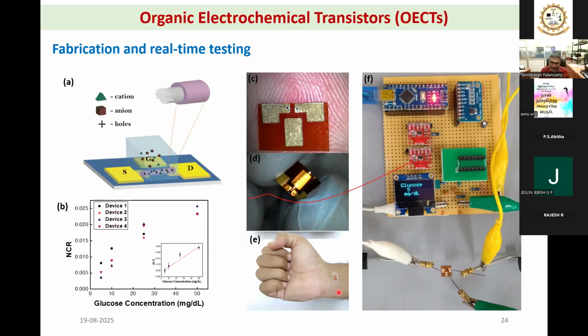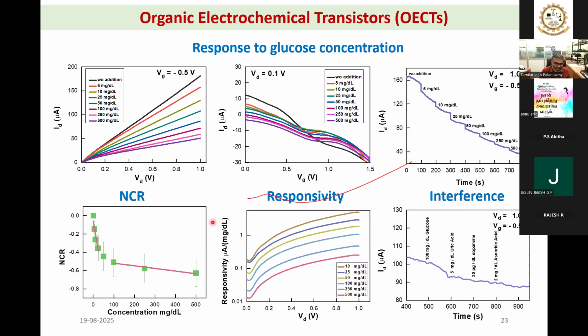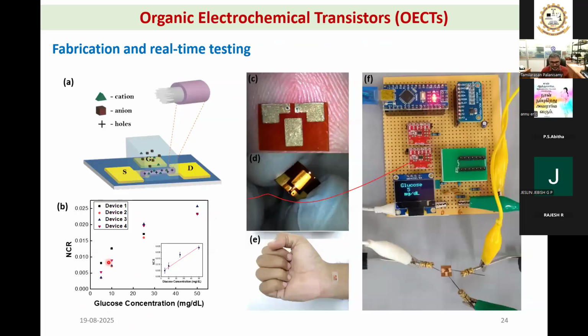So now, if you take the level in sweat, it will be typically 30 to 50 maximum. So if you see that range, 50 is somewhere here. So in this range, we have a very good responsivity. So that's why we use this device for sweat glucose. And you can see it's a very small device. And these two dots are actually the channel, and this is your gate.